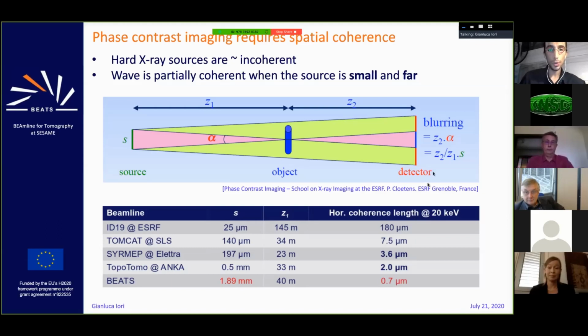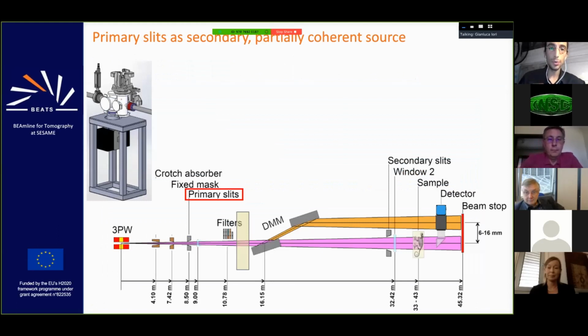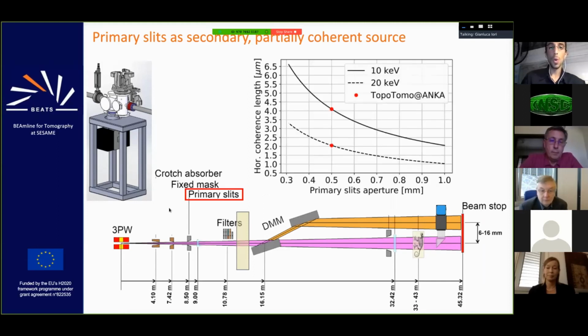So the solution for our case will be to work with a secondary source, which means that at 8.5 meters from the photon source, we will have primary slits, which will be closed to a size which is smaller than the original source size. And this allows to produce a secondary source with enhanced coherence. Of course, we lose in terms of propagation length, and most importantly, we lose photons. I can actually show how we have calculated how much this flux reduction will be, and we know that we can work with that, live with that.